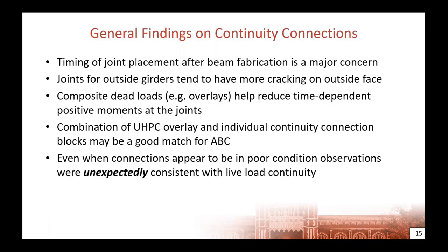And it's my observation that the outside face of the outside beam tends to crack first and seems to crack wider. Maybe an out-of-plane bending issue, and maybe it's just me, but that's what I observed. Composite dead loads, such as 2-inch high-density overlays and the parapet walls, help offset the positive moment from creep and